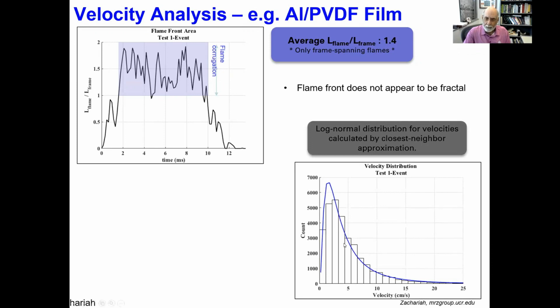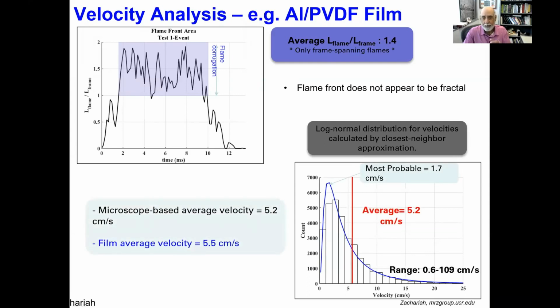And we can also get the PDF of the velocity distribution from these little microscopic regions. So you can see there are regions with very high velocities and low velocities, and this red line is the average. And the average of this curve corresponds reasonably well to the global average we see macroscopically.